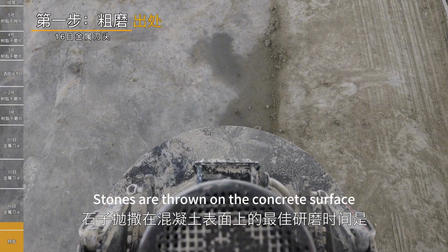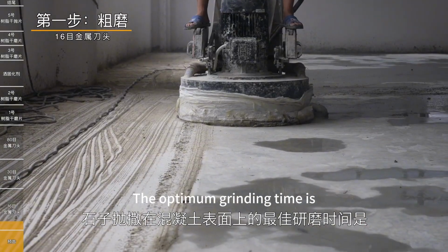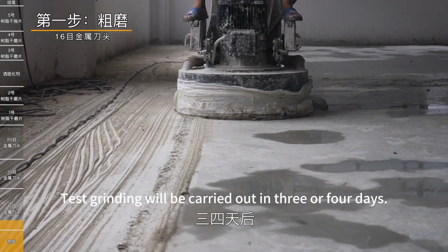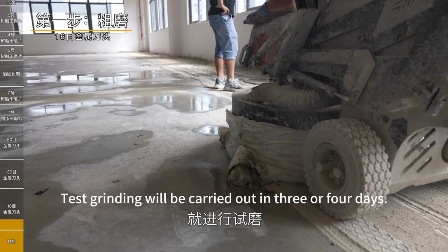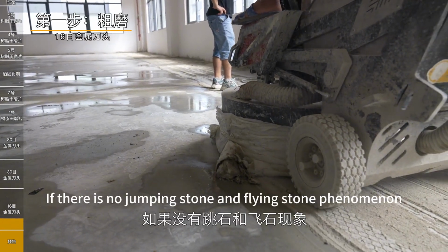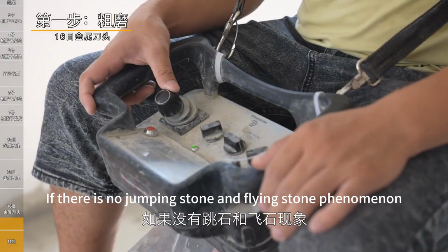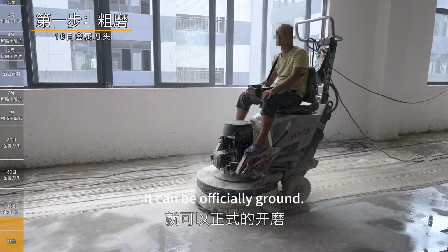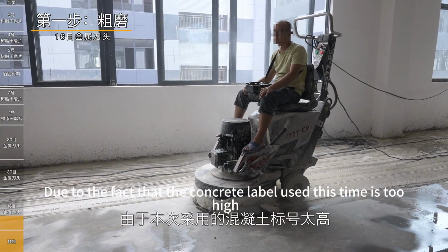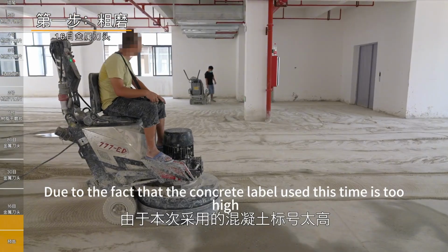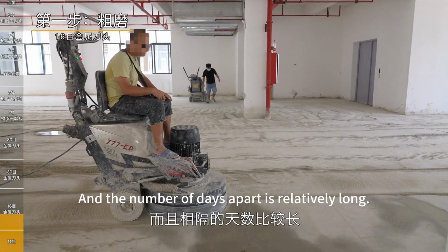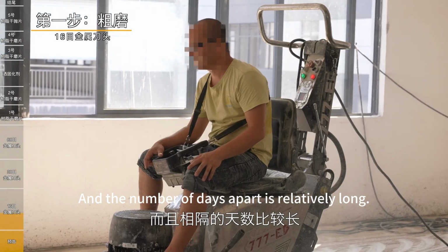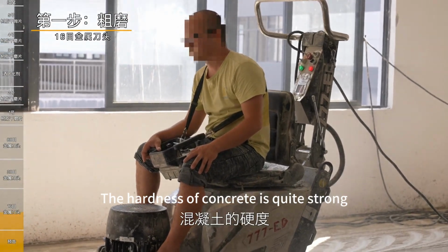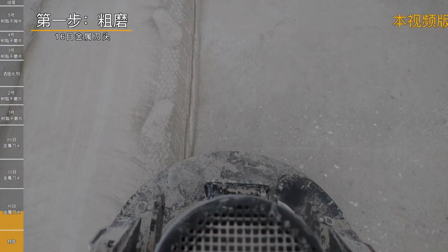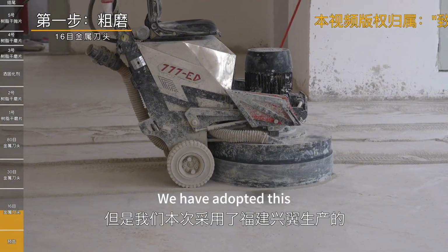Stones are thrown on the concrete surface. The optimum grinding time is determined by test grinding in 3 or 4 days. If there is no stone jumping or flying, it can be officially ground. Because the concrete grade used this time is too high and the number of days apart is relatively long, the hardness of the concrete is quite strong, but we have adopted this.